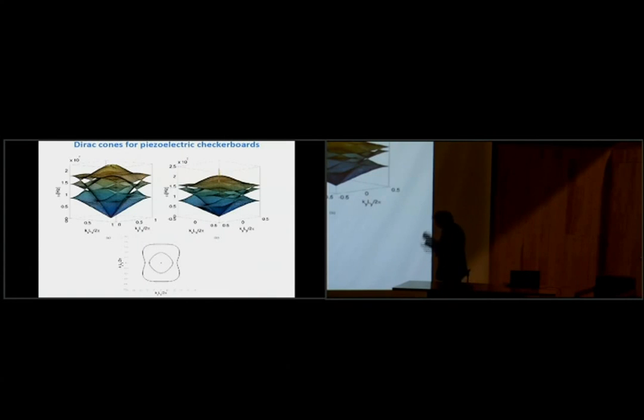One interesting feature that people probably don't talk about very much is the feature related to dispersion surfaces. So what does it mean? If I have a two-dimensional structure, then instead of plotting my dispersion diagram along the boundary of the Brillouin zone, I can take the function omega of kx and ky. Here they are normalized. And then plot a surface. Well, really, I need a family of surfaces. Here, I have a surface plot without piezoelectric effect. Here, I do have surface plot with the piezoelectric.